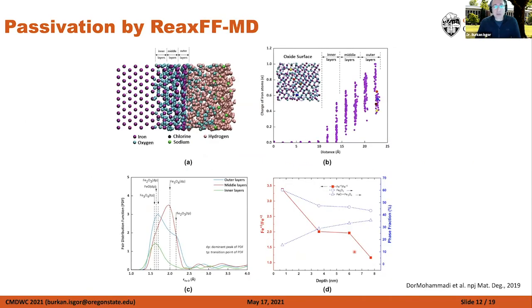I'm not going to go into those in detail, but I want to show some results, mainly from the molecular dynamics simulations. First of all, by simulating the passive film formation, we have shown that what we showed experimentally using XPS was confirmed. By looking at the distances between pairs of atoms, iron-oxygen atoms, we can look at what we call a pair distribution function, and the horizontal axis is basically the average distance between different atoms. You have these arrows showing the signature points of different types of oxides, and we see that the outer layers are mainly composed of Fe3 oxides. The inner layers are mainly composed of Fe2 oxides, and middle layers are a mixed bunch. This was a good confirmation.